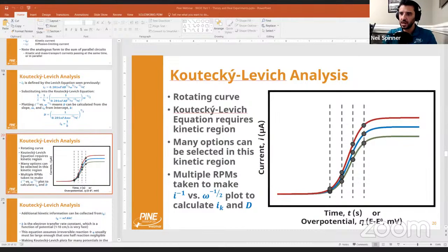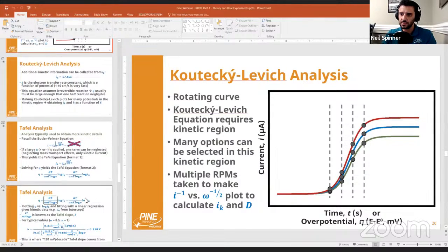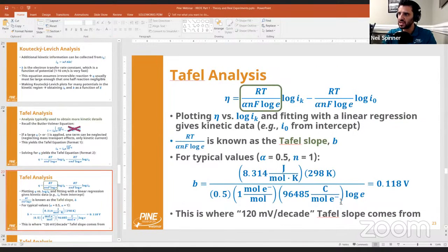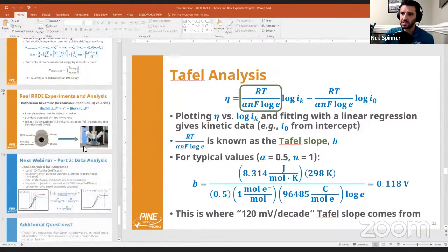basically you're getting a Tafel slope of, I guess, 20 millivolts per decade, right? 120 millivolts per decade. This is a webinar I did some time ago. So basically 120 millivolts per decade is a 1 electron irreversible process, a perfect, ideal sort of a thing. So in theory, if you're getting that divided by 6 electrons, you're telling me that you're basically measuring 20, I don't know, millivolts per decade, and that's too low. So what you want to measure is 30 or something, right? 30 would be over 4. So, you might just have to adjust the potential of your Tafel, where you're measuring your Tafel slope.